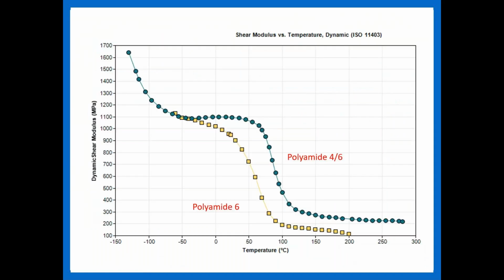Another way to look at that temperature performance would be something like this, a shear modulus versus temperature. So again, just a couple carbon difference. You can see that your nylon 6 starts to drop off and lose its stiffness at a temperature quite a bit lower, and then completely fails by 200 C versus the 4/6, which performs out to about 280-ish C. So again, just a couple carbon difference, but just enough for those hydrogen bonds and the crystallinity to take effect and end up giving you better heat performance in your 4/6 versus a 6.